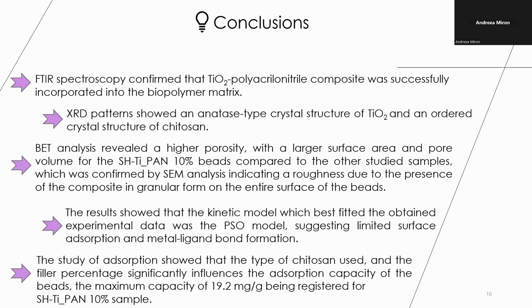The results show that the kinetic model which best fits the obtained experimental data was a pseudo second order model, suggesting limited surface adsorption and metal ligand bond formation. The study confirmed that the adsorption depends on the type of chitosan and filler percent, and that the beads with chitosan from shrimp shell waste and 10% of composite are the best.